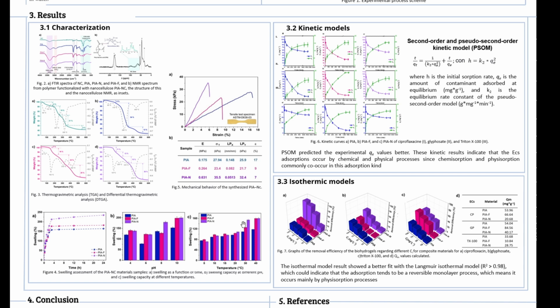In the case of the swelling capacity, it was evaluated, and it can be observed that the biohydrogels are hydrophilic due to their structure and ability to form hydrogen bonds. The swelling behavior of the samples under different pH and temperature conditions shows that the polyitaconic acid biohydrogels have a lower swelling capacity than counterparts containing nanocellulose.